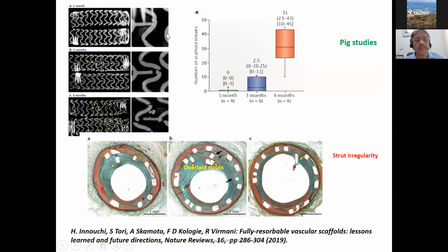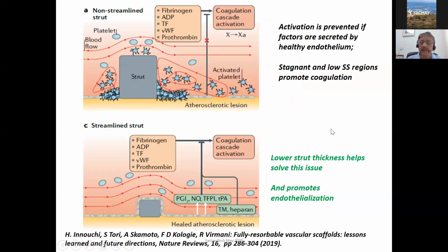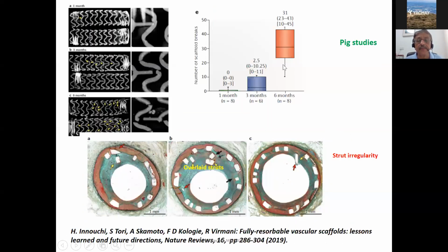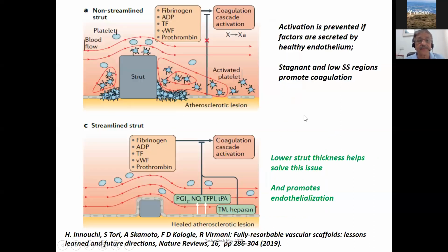And one of the major problems was fracture. Fracture happens at the joints of the struts, which are stress concentration points. So in contact with bodily fluids, these stress concentration points fracture, and the number of fractures increases over time, as can be seen here. There are also other problems with deployment, such as overlaid struts and strut irregularities, which I will not talk about. But the basic problem is really the fracture, as well as the lack of endothelialization.